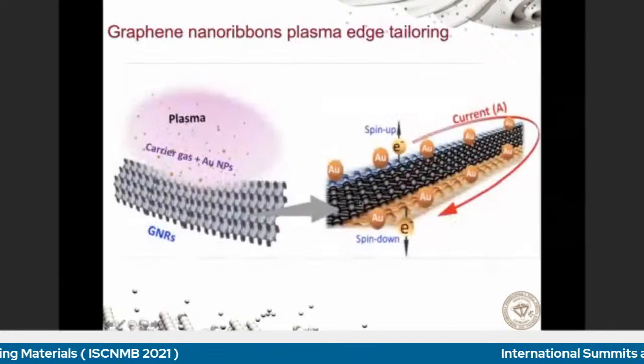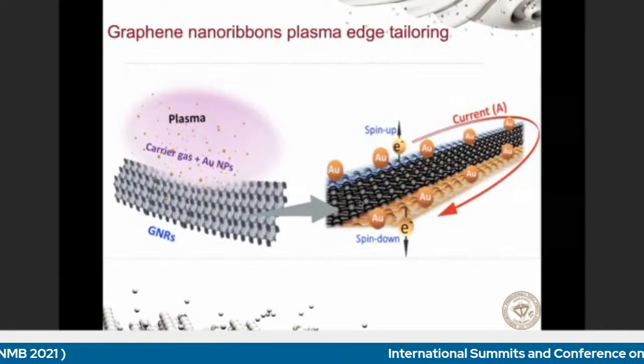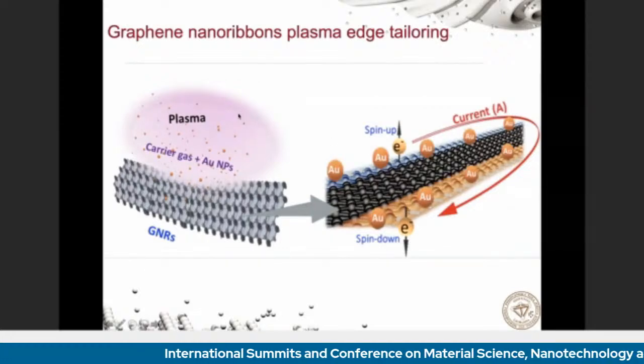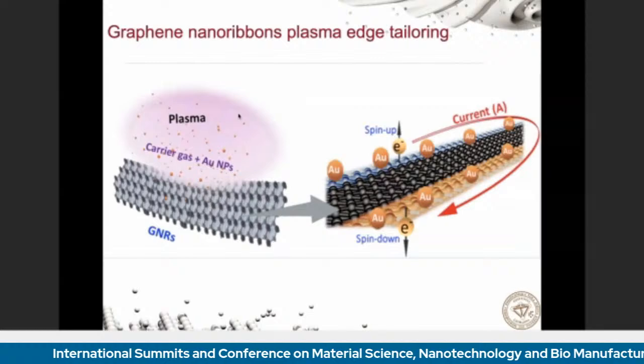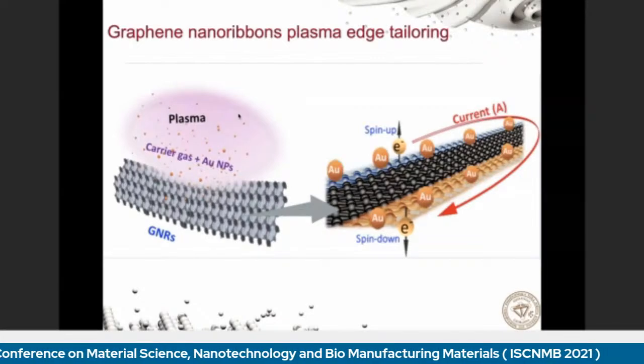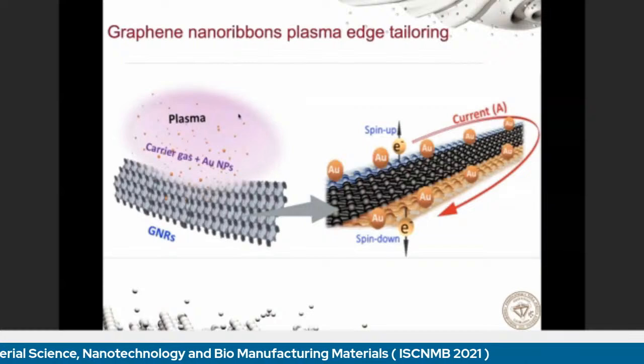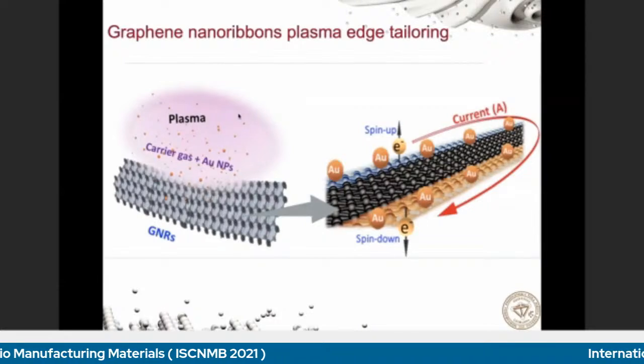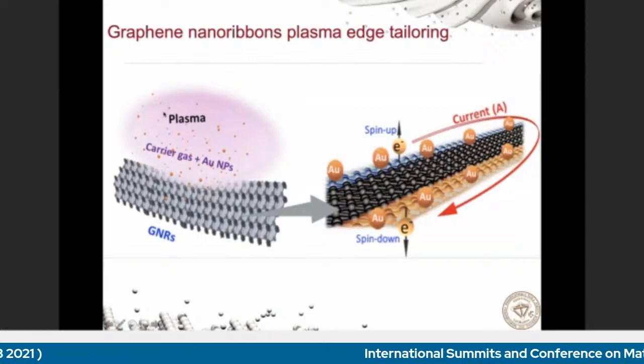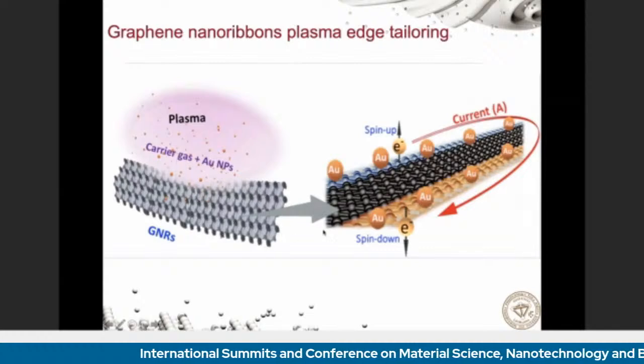Then we are talking about so-called plasma-assisted tailoring, which means that what is being used is low-energy plasma, some carrier gas, which has golden nanoparticles. So our doctoral student, Aswati Vasudevan, is actually doing these experiments. She also prepared all these beautiful images. And what happens is that these golden nanoparticles, the gold atoms attach to the edge of the graphene sheet.